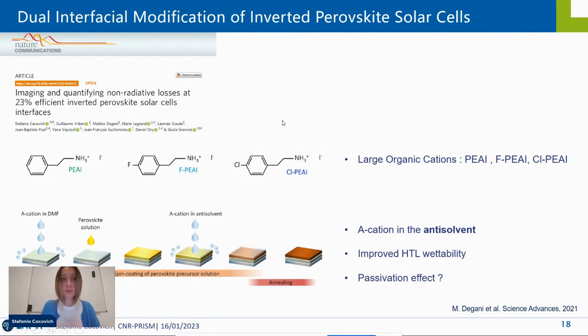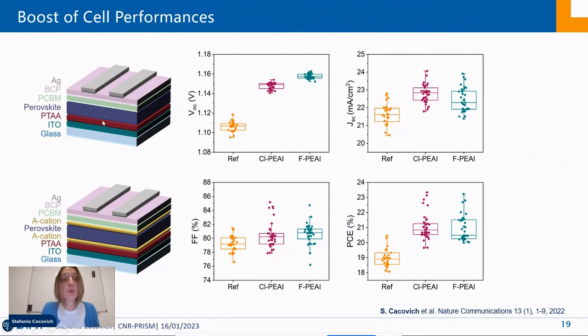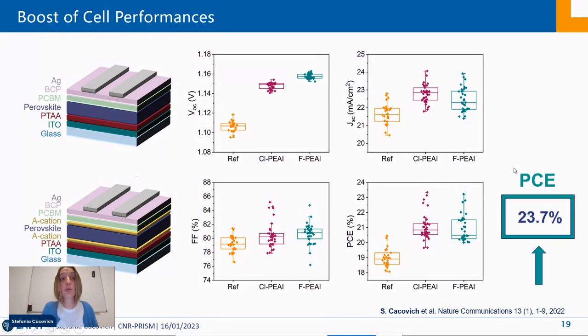So here, what we wanted to study is a dual interfacial modification of inverted perovskite solar cells. Basically, we wanted to compare a reference cell, where we have all the photovoltaic characteristics, figures of merit, with a cell where, by adding this organic cation at these two interfaces, we obtain a boost of cell performance that went up to 23.7%. And this is one of the highest values ever reported for an inverted solar cell architecture. So it means we have a PIN architecture with record VOC.